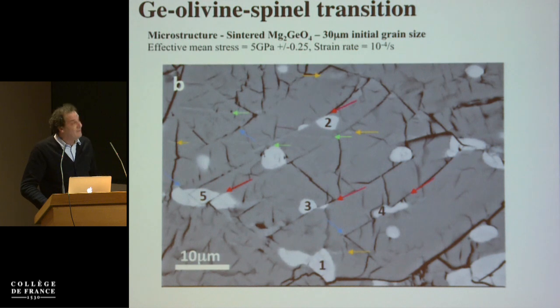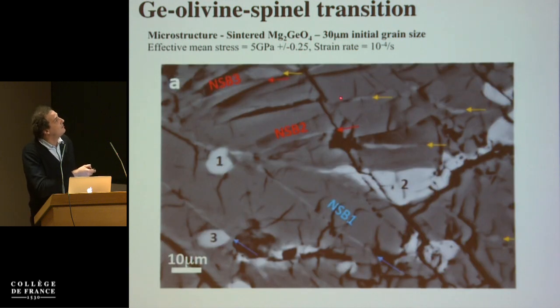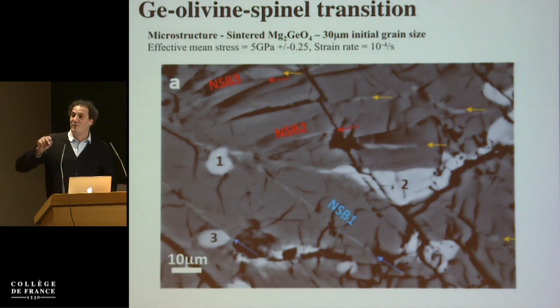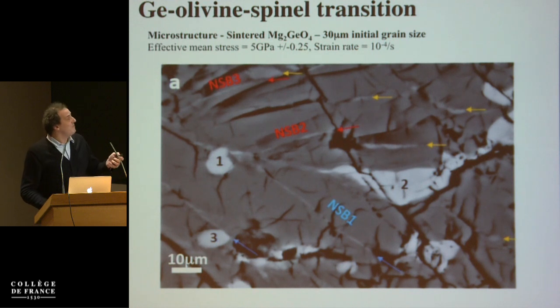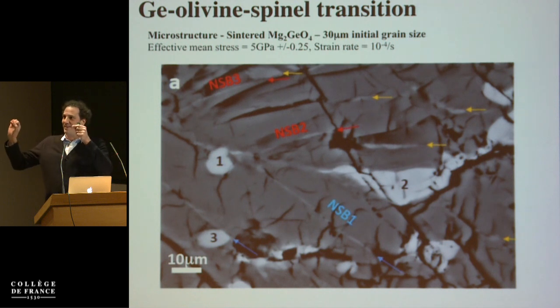So we see this about everywhere in the sample. This is another example where we see those very nice parallel features. I want to say that there is some evidence for intermediate and deep earthquakes, when people do back projection, where they see two foci propagating almost together. So maybe our idea that an earthquake is just one single fault propagating in these conditions might not be the case. You might have several faults propagating at the same time, which could explain the large CLVD component we see.